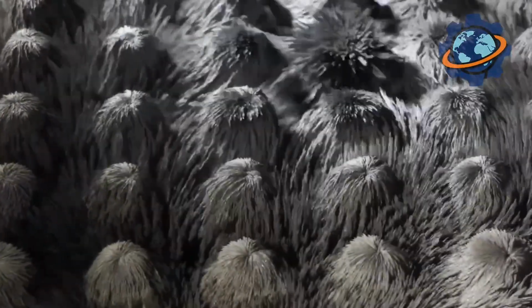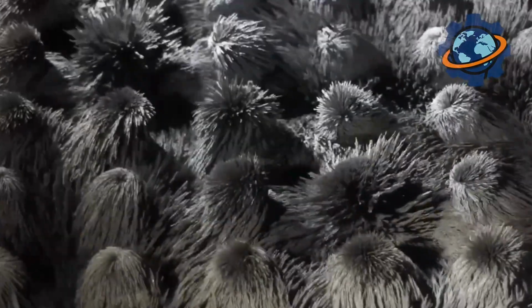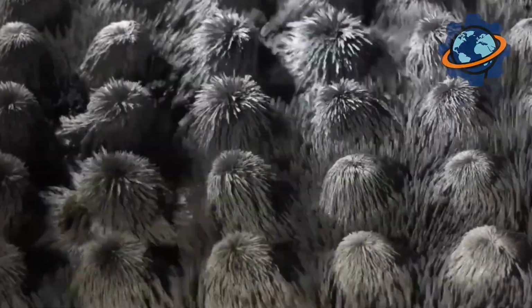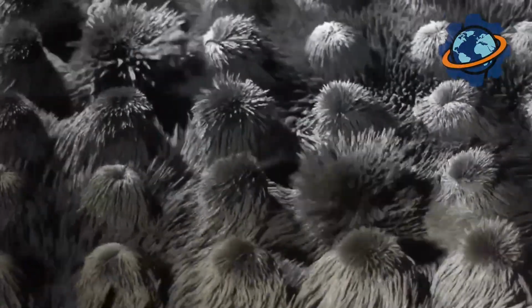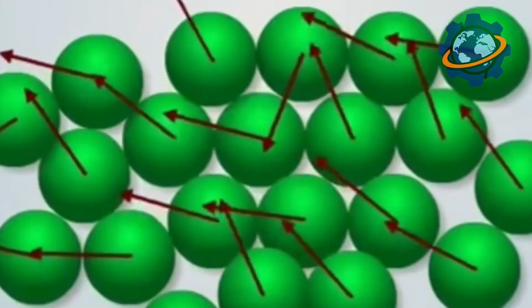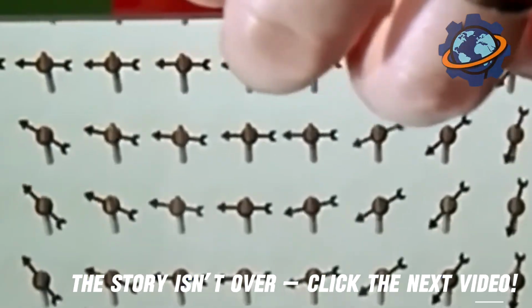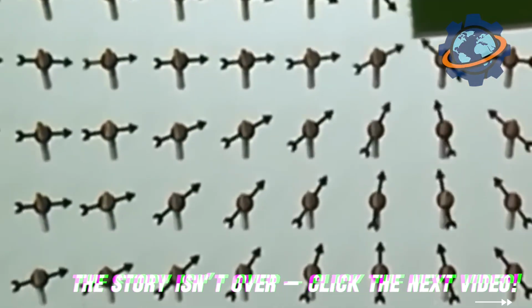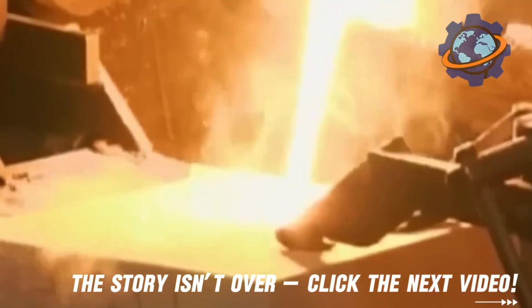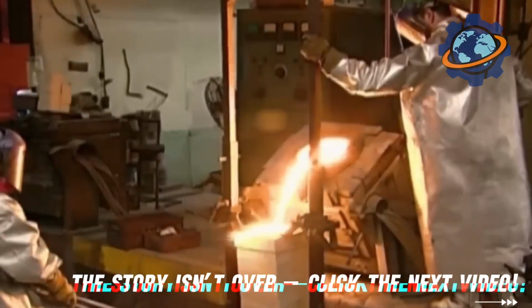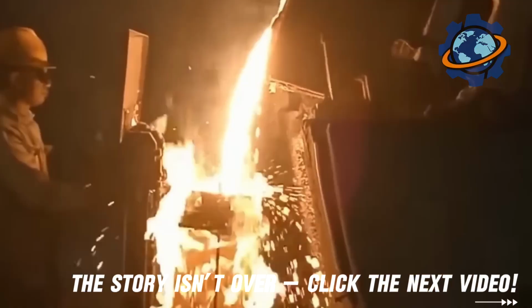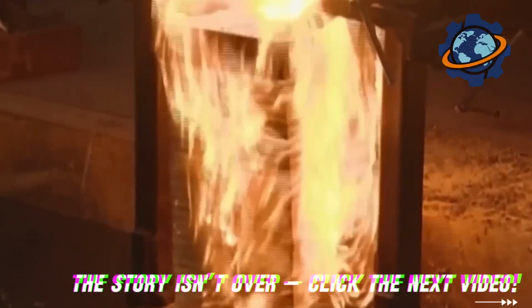This unique microstructure, with very fine, often anisotropic grains, is the key to the high strength of neodymium magnets. The smaller the grain size, the more difficult it is for the magnetic domains to change their orientation, which provides high resistance to external demagnetizing fields. Thus, the alloying and rapid cooling stage is fundamental for forming the magnetic characteristics that will later be locked in during subsequent production stages.